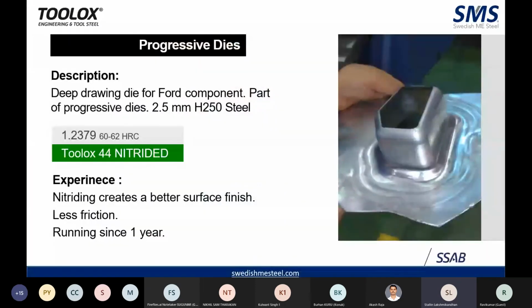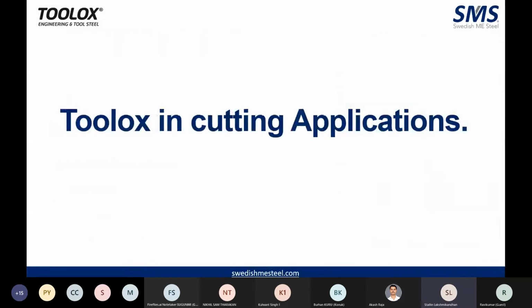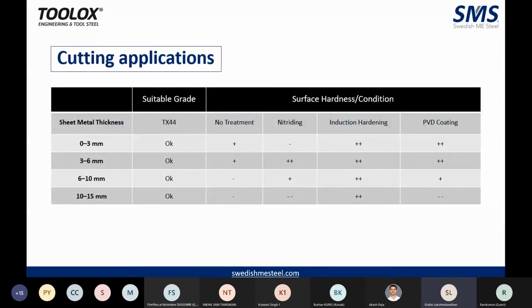Another example is progressive dies. Now let's look into Toolox in different cutting applications. If the sheet metal you want to cut is between 0 to 3 mm, then you can use either Toolox 44 as it is, or you can go for induction hardening or PVD coating. Nitriding with Toolox 44 is not recommended when the sheet thickness is less than 3 mm. When the sheet metal thickness is 3 to 6 mm, you can do all three processes depending upon what you want.